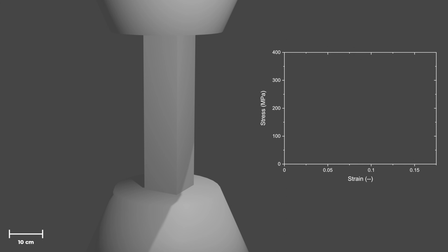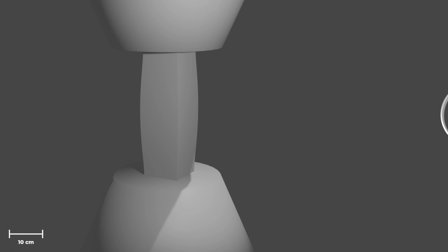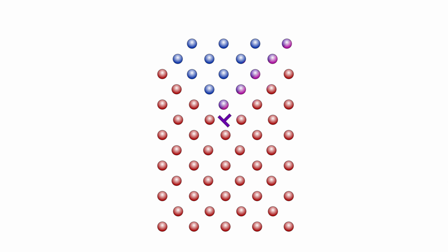If large enough stress is applied, metallic materials can deform plastically, which is an irreversible process. The plastic deformation is usually mediated by dislocations, which are line-like defects in the crystal lattice. If stress is applied to the sample, the dislocations start to move from the interior of the sample towards its surface. Due to high dislocation density, typically more than 10^13 dislocations per square meter, the